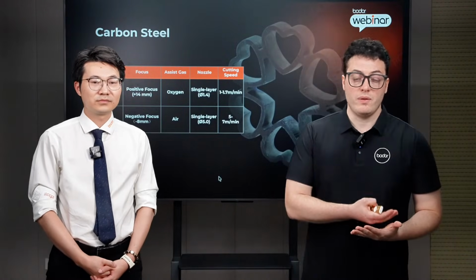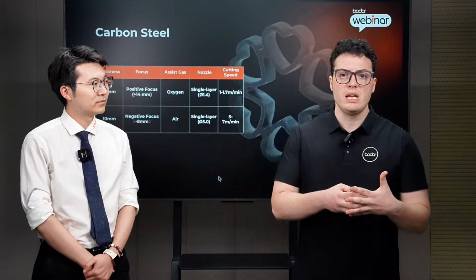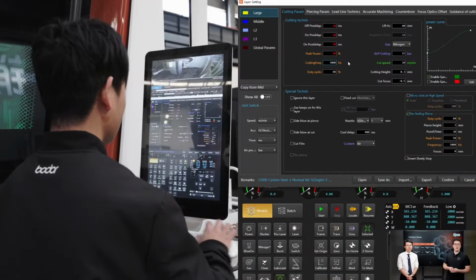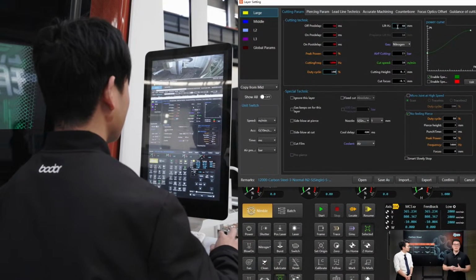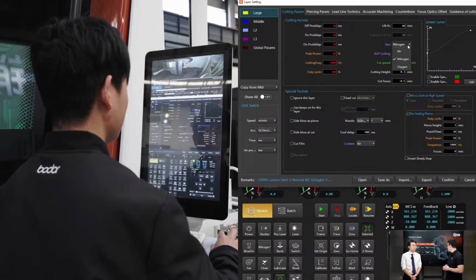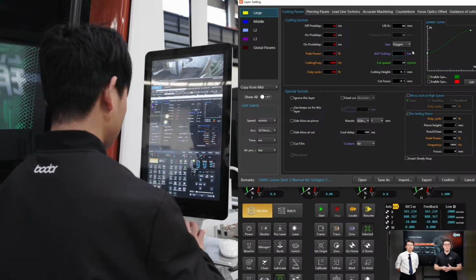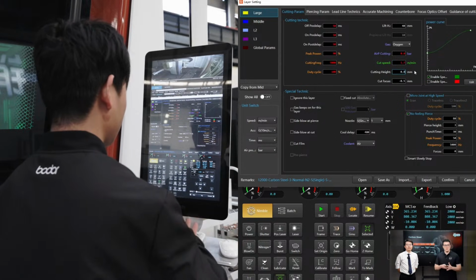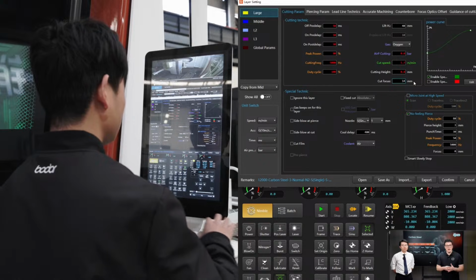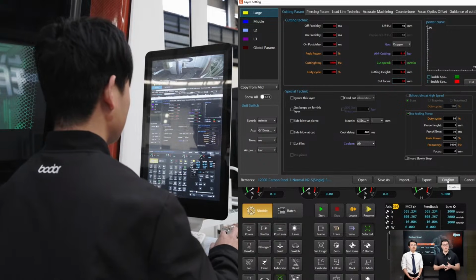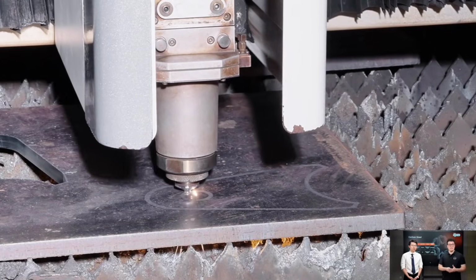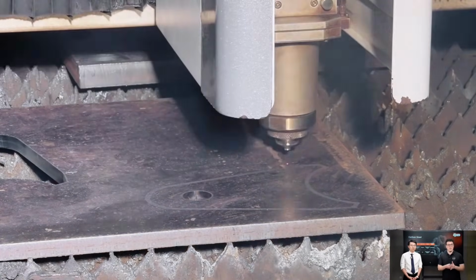Today we will look at two representative cases. One for thick plate, and one for medium thin plate. And we will use both positive and negative focus so that you can clearly see the difference. Right now, what you are seeing on the screen is a 16 millimeter carbon steel plate cut with a positive focus. For this cut, the focus position is set to about plus 14. We are using oxygen as the cutting gas and a single layer nozzle with a diameter of roughly 1.4 millimeters. These settings give you stable cutting performance on thick carbon steel.